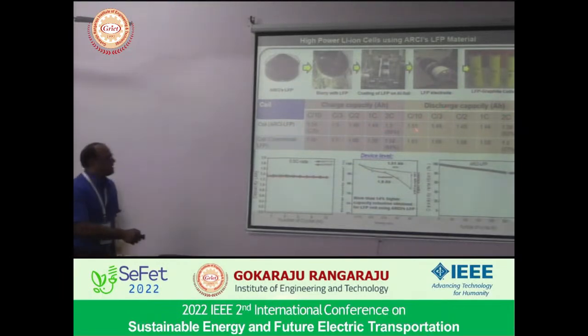If you can see the discharge capacity, this is 1.51 ampere hour, the cell which is made from the ARCI LFP, slightly lower than that commercial LFP. But if you can see the capacity retention even at a fast charging rate, the cell made from ARCI LFP is able to retain 92% of capacity, whereas the cell made from the commercial LFP can withstand only 77% capacity retention. And when we are estimating, more than 14% higher capacity retention was obtained for the LFP cell made from our indigenous ARCI LFP, and the cycle life, everything is better.